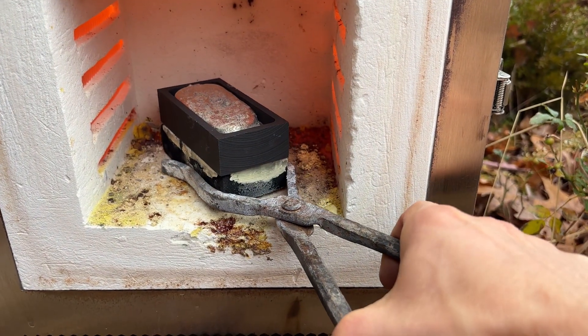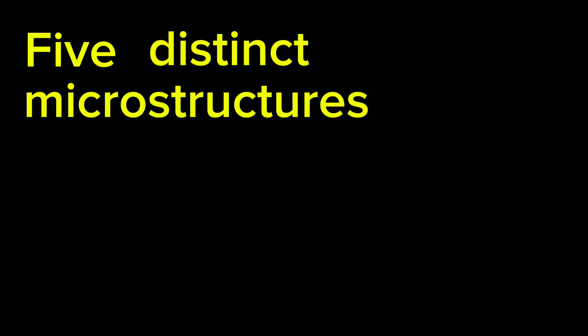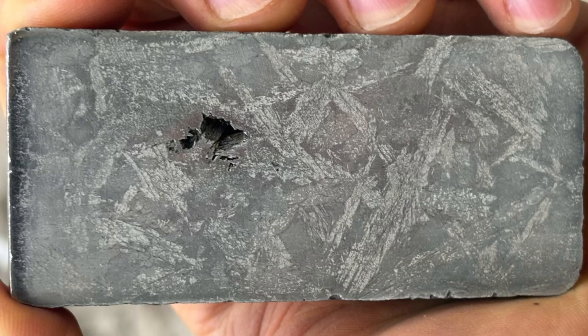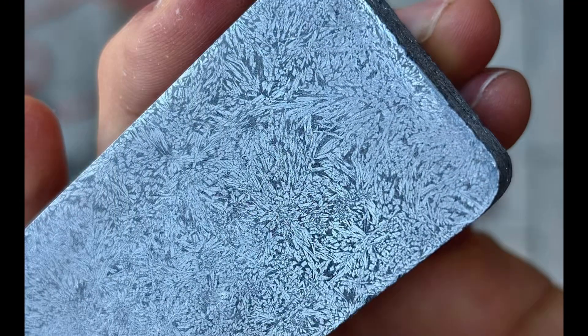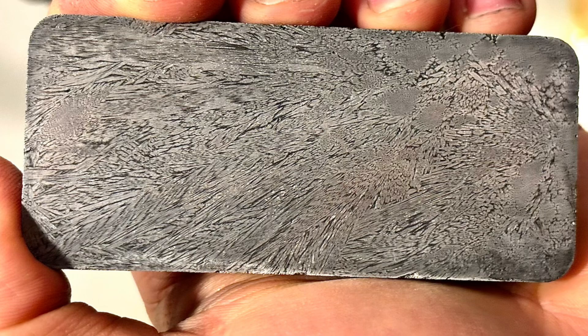After slow-cooling, grinding, and polishing, we have five distinct microstructures. The pure 45-55 Al-Cu alloy has large wide theta aluminum rods paired with dendrites. The 3 weight percent zinc ingot has similar rods and dendrites but looks a little more unstable. The 8 weight percent zinc ingot takes a different structure altogether, with the rods disappearing and the intermetallic dendrites becoming snowflake-shaped. At 12 weight percent zinc we see extremely long intermetallic crystals with a feathery appearance, and at 18 weight percent zinc we lose large microstructural features altogether.